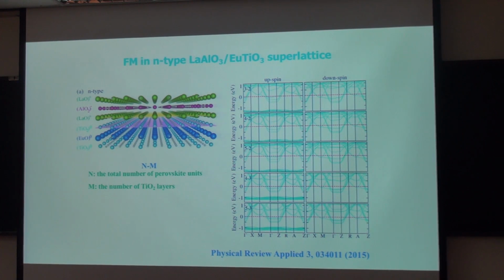The first case is the n-type superlattice, where the system is regarded as electron doped. We can find a formal band gap located here. The conduction band is partially occupied, and the system is also spin polarized. And the two-dimensional electron gas, or the conductive state, is composed mainly of the titanium 3d electronic state.